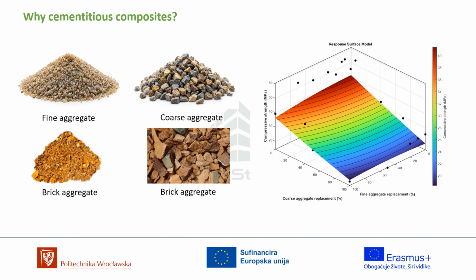However, such results are inferior to the results obtained for fine aggregates. We reported only the results when the replacement was done for one particular material, either fine aggregate or coarse aggregate. However, combining all of these in a chart and also providing the replacement of both aggregates with various replacement ratios, it can be seen that unfortunately the behavior of the hardened materials is similar, in that it decreases the value of compressive strength. However, looking closely at the trend, it is still possible to design a mixture that meets the requirements of construction materials.